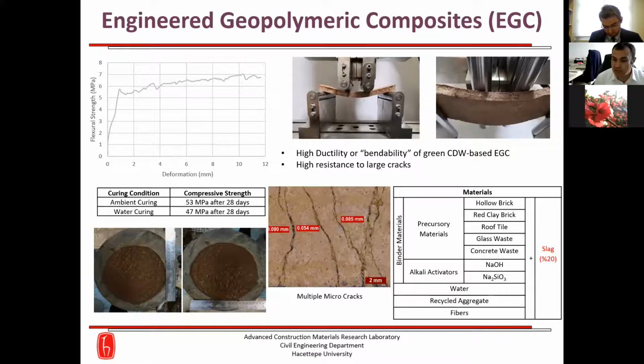The figure on the upper left side shows the typical flexural stress deformation curves of the EGC containing around 1.5% polymeric fiber. And the characteristic of the flexural hardening after the first cracking is accompanied by multiple micro cracking. And the crack width development during the inelastic straining is also shown in the middle of the presentation. There is a photo that shows the crack characteristic of the specimens.